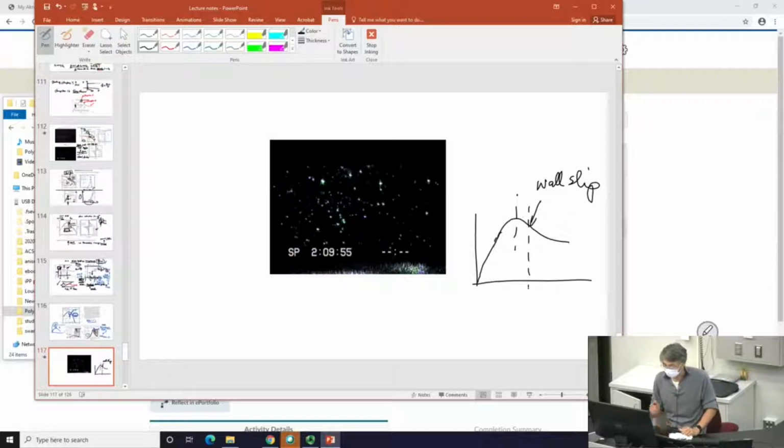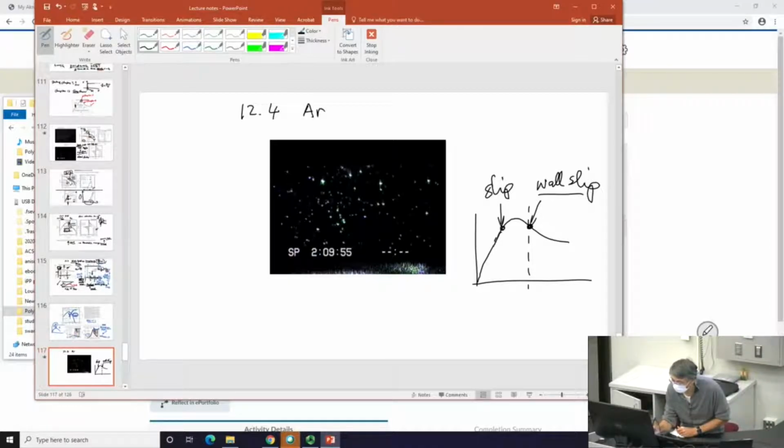By particle tracking velocimetry, we could visualize how it happens and answer the question that you require certain conditions for wall slip to occur. So by the same token, just like the case of shear banding, where failure occurs internally, if wall slip is to occur here, can I anticipate slip to occur here if I stop shearing here? So it's the same physics as we did in the bulk. So we predict, this is section 12.4, this so-called arrested wall slip. So I can predict that wall slip will take place earlier by me terminating here.